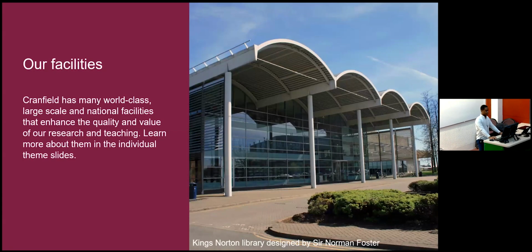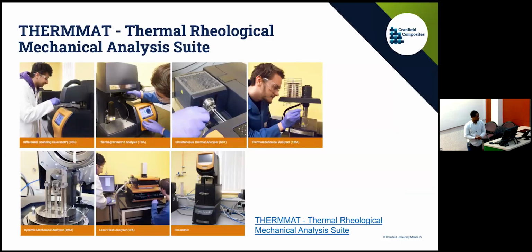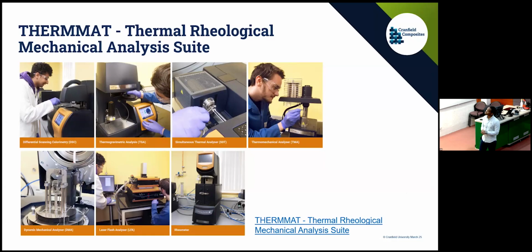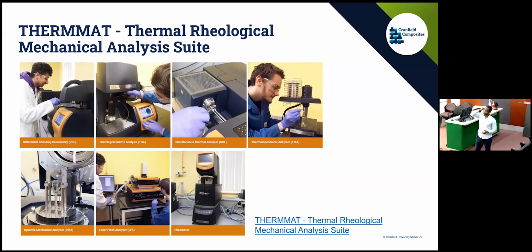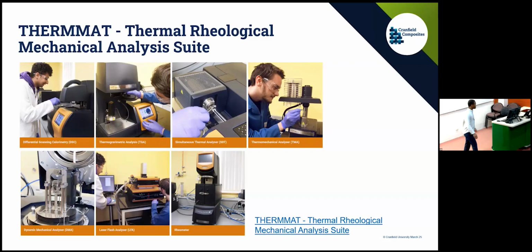So the last thing I'll talk about is a bit around our facilities, which I think could be quite useful and helpful to everybody in the room and on the call. So we have a large thermorheological and mechanical analysis suite. We call this TherMat. And we have quite a lot of the kit that you guys have here, with the addition of the laser flash analyzer, which measures thermal conductivity and diffusivity up to 1,200 degrees, as well as TGA, which separated out from the SDT, which goes, I think, to 900 degrees.